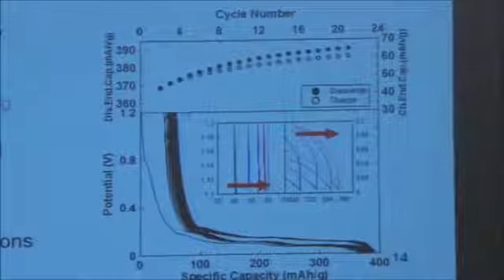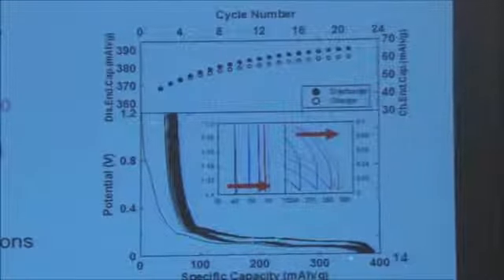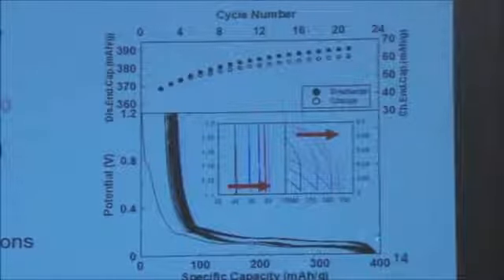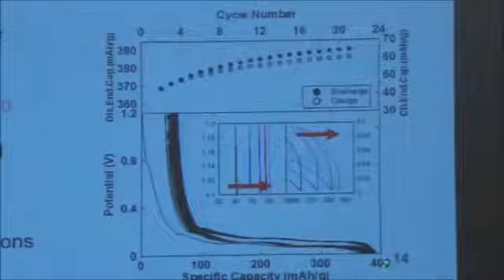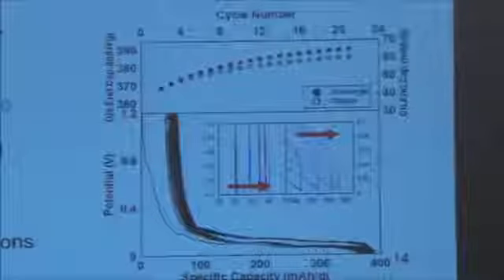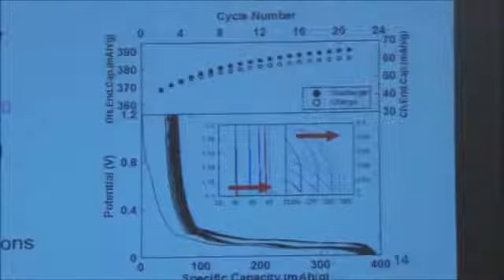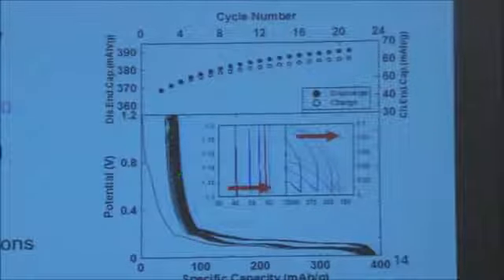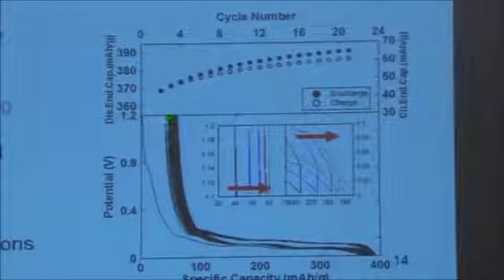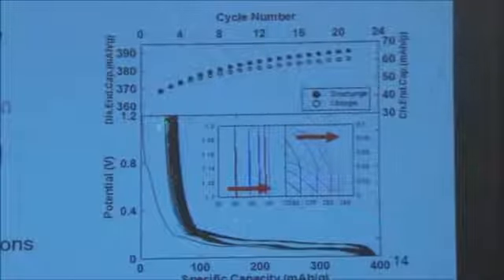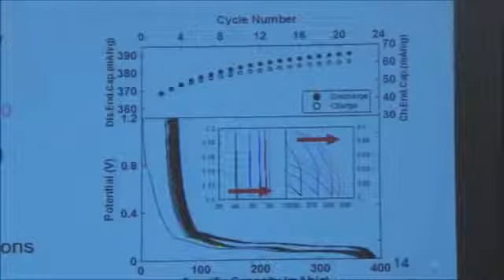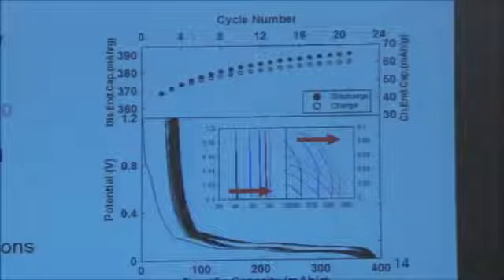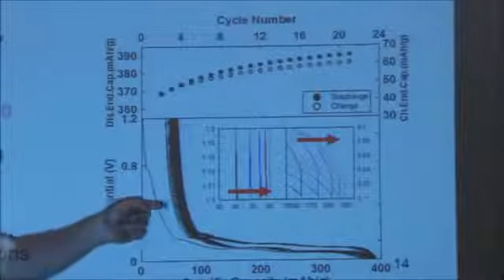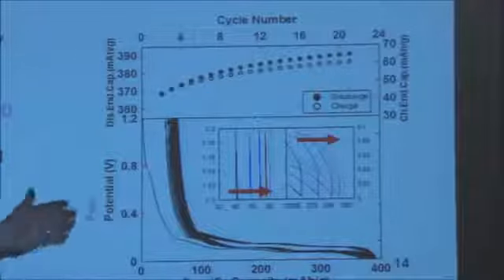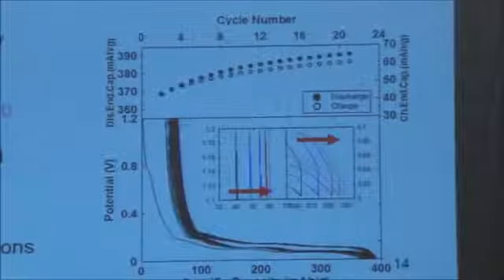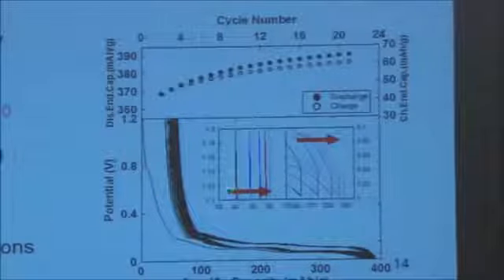That's because some of the lithium that you've transferred to the graphite side has reacted and formed the solid electrolyte interphase. Some of the components in that interphase were lithium oxide, lithium carbonate. They trap lithium atoms. So when you come all the way back, the graphite is empty of lithium, but some of the lithium that you added is in that SEI and doesn't come back. And as you charge and discharge repeatedly, this voltage curve keeps shifting to the right, always. That comes about because some of the lithium is being trapped in that SEI film.